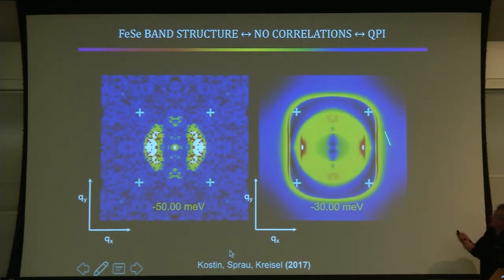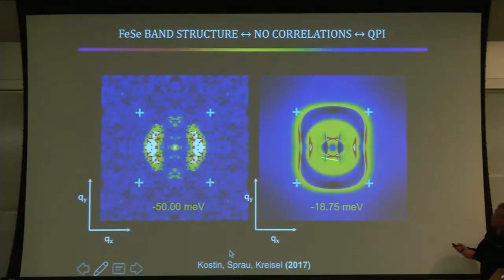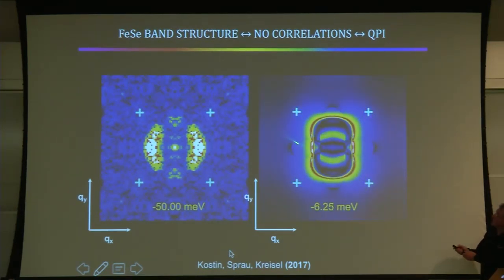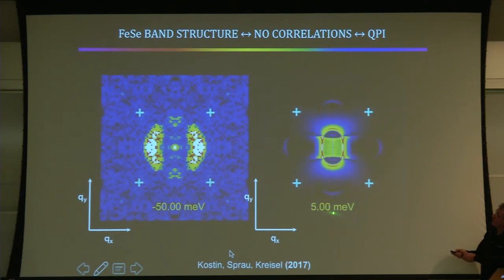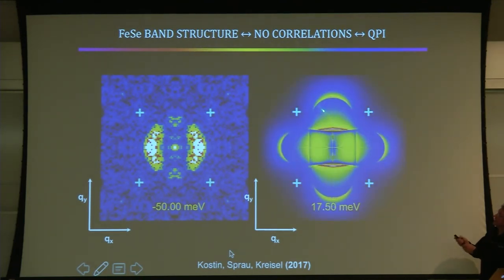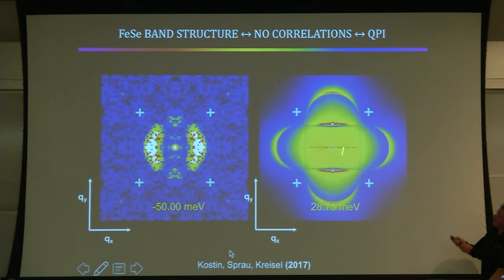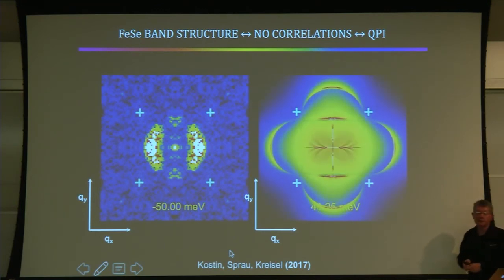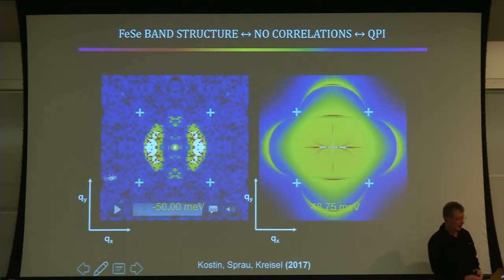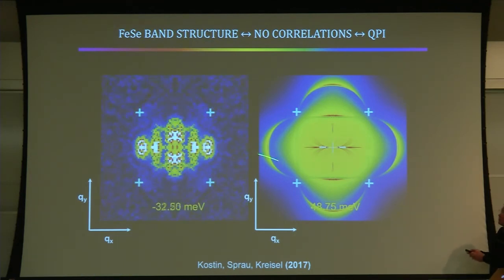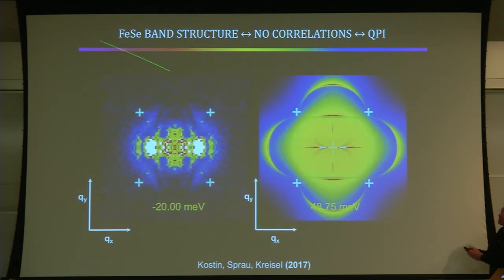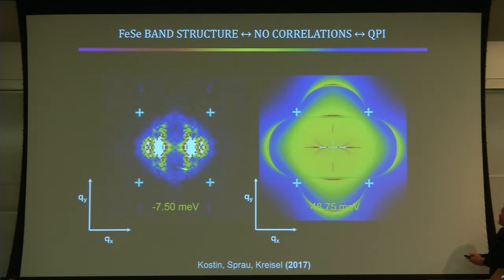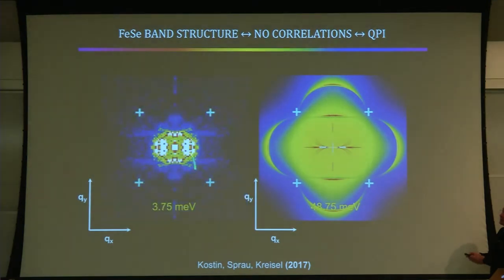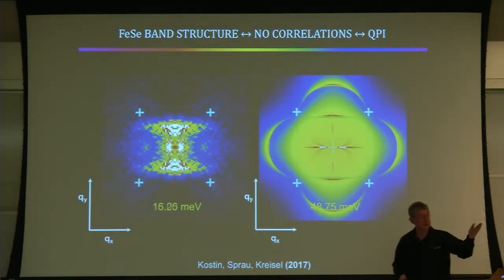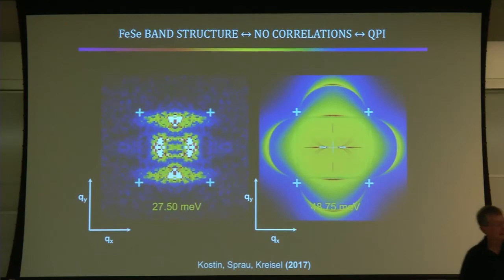You see it's reasonably isotropic, but it's C2 symmetric. It approaches the chemical potential. It passes the chemical potential. It rotates. This is the dxy band out here, and this part rotates and disperses in the opposite direction. That's the prediction. It's completely inconsistent with the data, which disperses only along this direction. There's no dxy band. We don't see it, and neither does photoemission. But it does rotate at the chemical potential. So that's one prediction, fully coherent, no orbital selectivity.